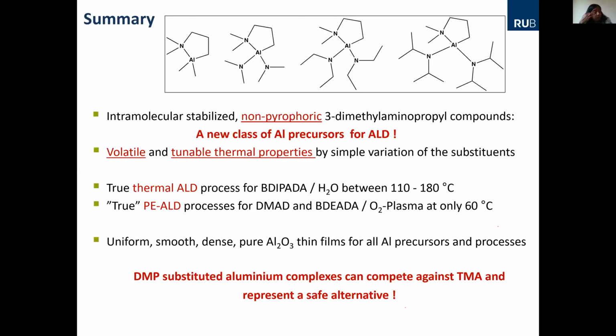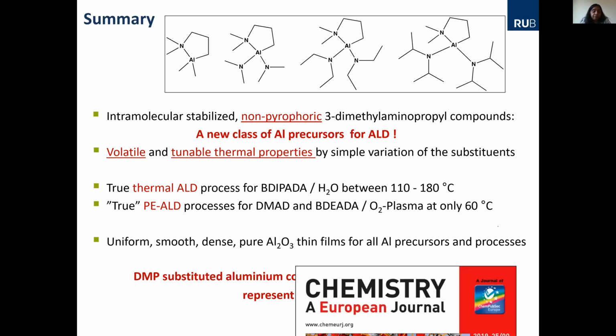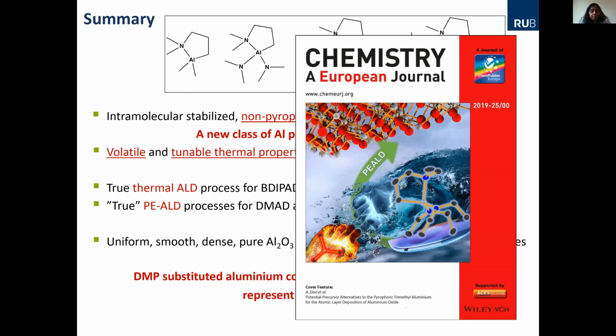So we want to summarize in this case that we do a lot of precursor chemistry, test them for CVD or ALD, and in this particular case, we had a non-pyrophoric precursor, which is quite relevant, as I said, because you would like to minimize all the safety issues. And in terms of cost, it's also an advantage. We assume that the DMP-based precursors can compete very well with the commercially available precursor. So this was published last year or so in Chemistry European Journal.